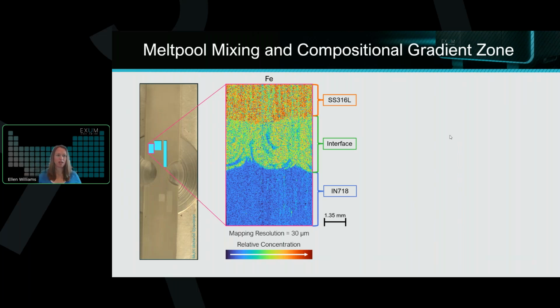So then that allows us to do smaller areas with much higher resolution to really investigate that interface that we were looking for in this study. So here we're looking at this smaller area with a 30 micron laser spot size, so giving us a higher resolution look at these really 3 distinct areas that we see here. So of course, where the iron is low, that's our Inconel 718. Where the iron is high, that's our 316L. But then we've also got this area where iron is moderate or medium, and that's our interface.